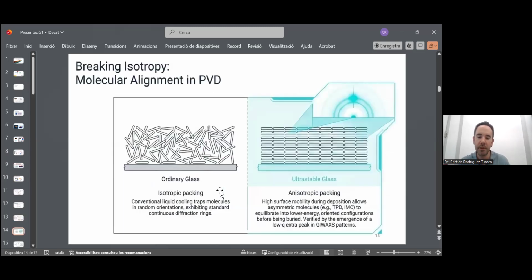Let me explain other properties of ultrastable, of vapor deposited glasses, which is very important in this case. You know, ordinary glasses are isotropic, okay. By definition, one would expect that the glass is completely isotropic, but when we grow the material by physical vapor deposition, we can get some kind of anisotropic packing. Okay, this is just a scheme, this is not the real scenario. This would be a crystal. An ultrastable glass is not that perfectly aligned, but it's way more oriented. It has some degree of anisotropic packing, which depends on the deposition conditions.